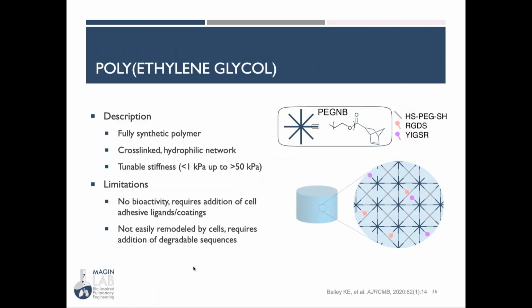Of course, my favorite material. I did my postdoc in Christy Anseth's group, and so I spent a lot of time looking at and learning about polyethylene glycol. This is, again, a fully synthetic polymer. It can create a cross-linked hydrophilic network, and it has a tunable stiffness somewhere between 1 and 50 kilopascals, not quite as stiff as PDMS. In our lab, we use PEG norbornene quite a bit and a few other PEG-based polymers.